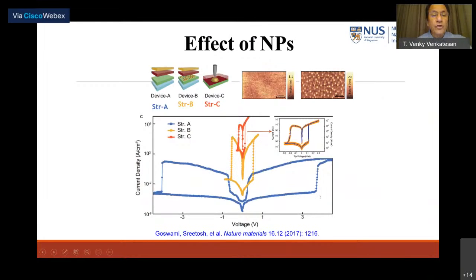Now, let's go to device B, where on the indium tin oxide, we deposit a bunch of gold nanodots. What those gold nanodots do is they locally enhance the field. So in device B, you see, suddenly the switching voltage dropped from 4 volts to 0.4 volts, a drop by 1 order of magnitude. The current going through the device jumps up by 2 orders of magnitude.